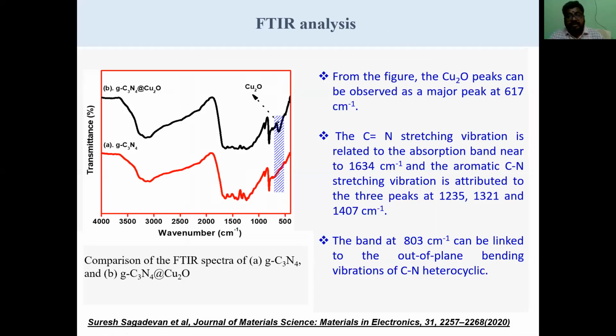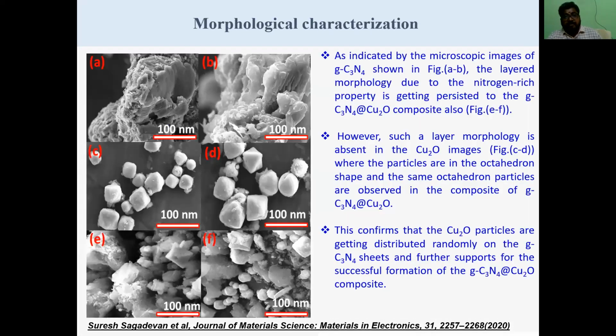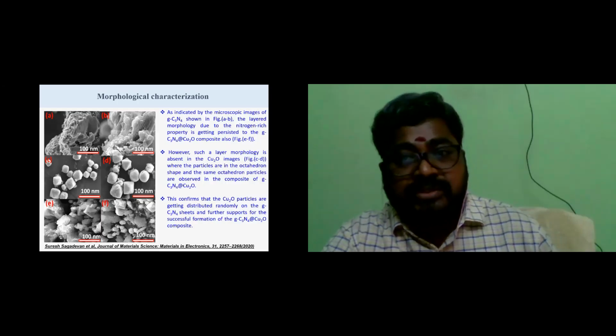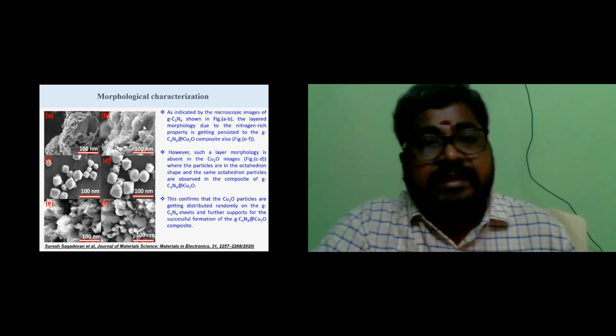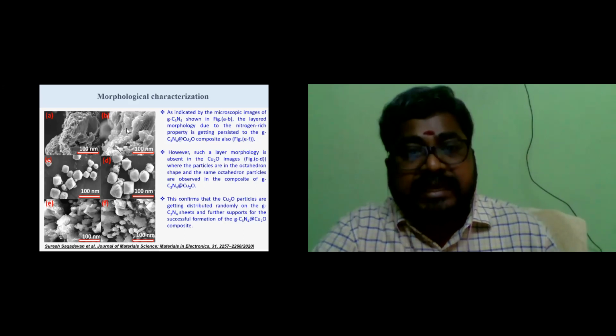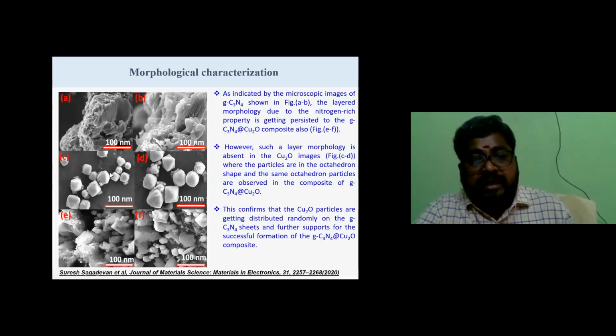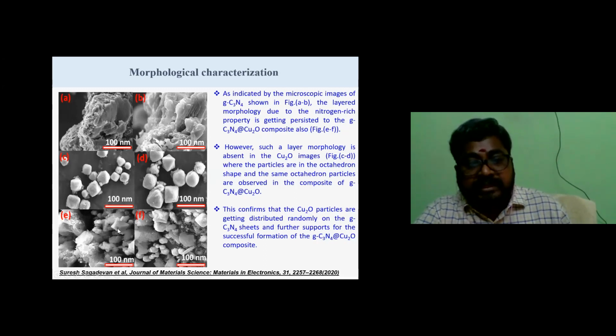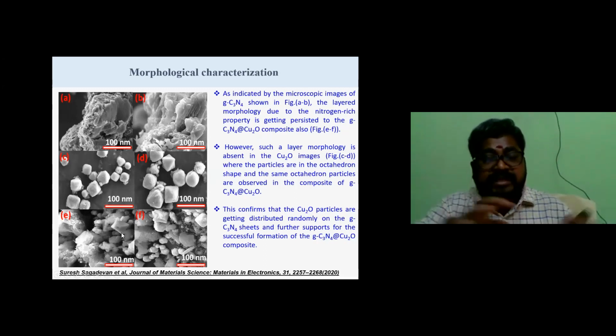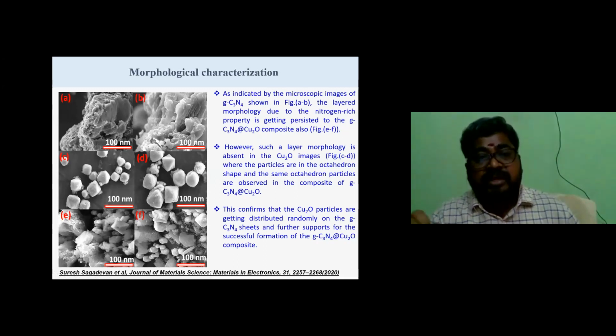Oh, okay. These are all FTIR analysis, which also confirms that. These are all optical properties. You can see that the first figures, A and B, show the graphitic carbon nitride surface morphology, a sheet-like morphology, and then this one is the octahedral shape of cuprous oxide, and the third, images E and F, show the octahedra randomly distributed on the g-C3N4 sheet. This also confirms the successful formation of the graphitic carbon nitride with cuprous oxide.